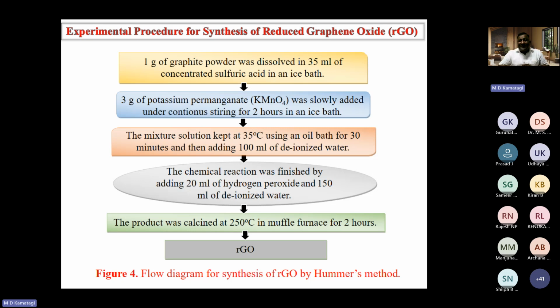This is the procedure of synthesis of reduced graphene oxide from graphite powder. So 1 gram of graphite powder was dissolved in concentrated sulfuric acid. 3 grams of potassium permanganate was slowly added to that 1 gram of graphite solution under continuous stirring for 2 hours in an ice bath. The mixture solution was kept at 35 degrees Celsius using an oil bath for 30 minutes, and then we added 100 ml of deionized water.